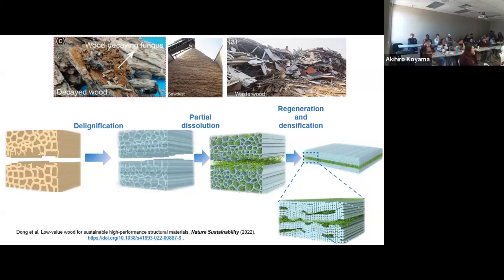And we do partial dissolution of the cellulosic component that is left in the wood material. We're not dissolving the whole wood. We're only dissolving the very top interface or layer of wood. And then by putting this material in water, what you're going to achieve is these cellulose chains that I described earlier are going to be there in green color, highly hydrated. And in a process that is called regeneration, followed by densification, they will start to bond the pieces together. So it's a form to glue pieces of wood back into a material that contains the same components initially. It's the same cellulose that existed in wood, just that we dissolve that cellulose that is only on the surface.